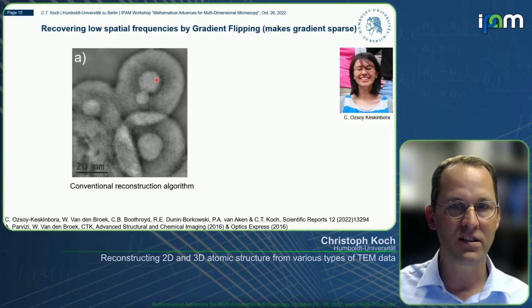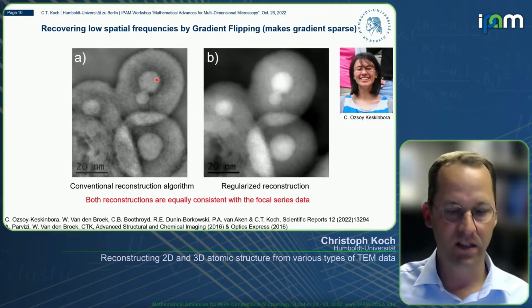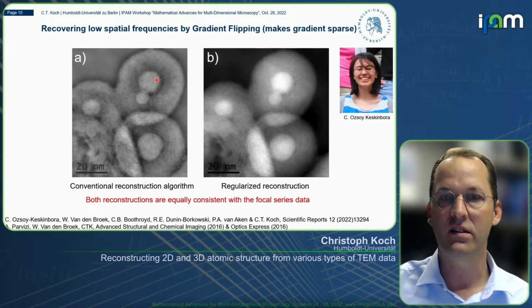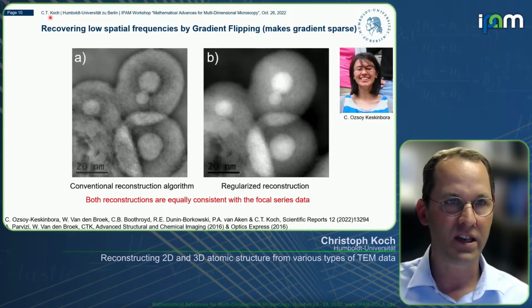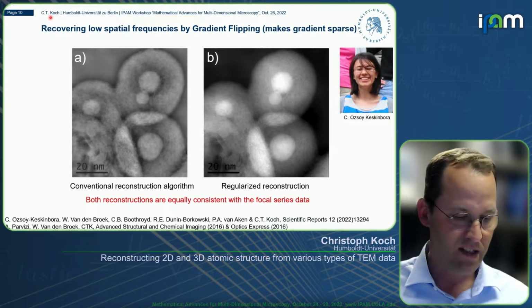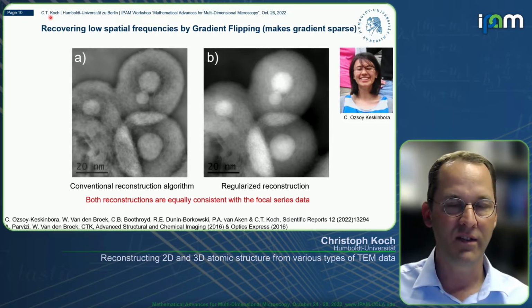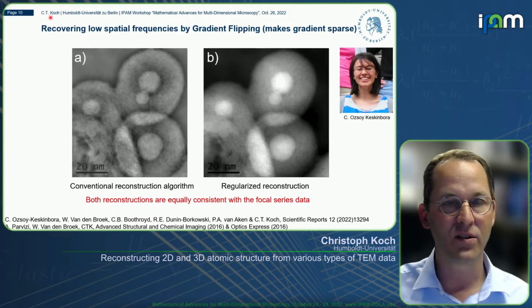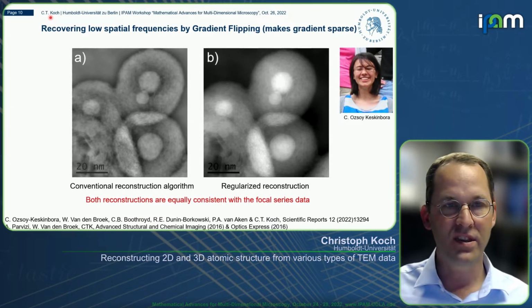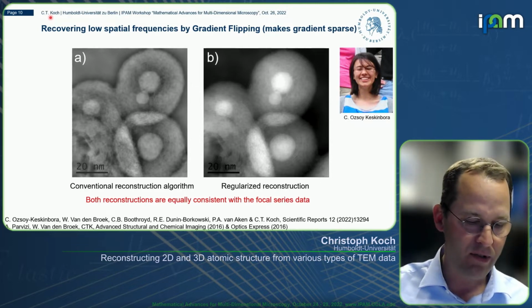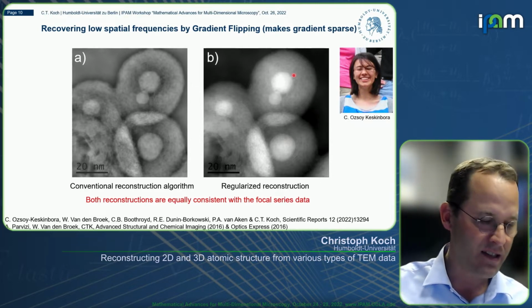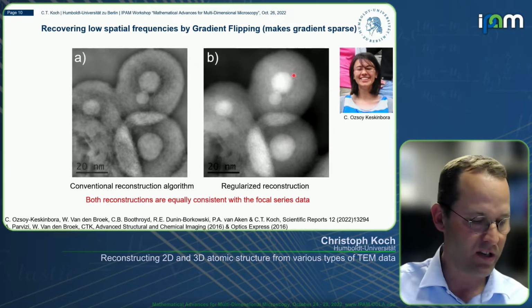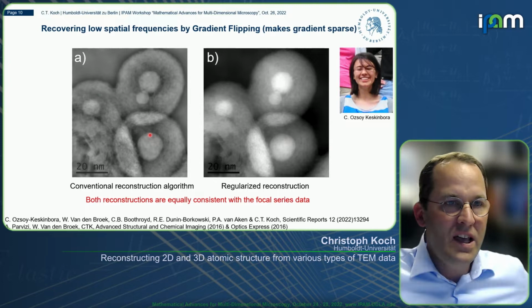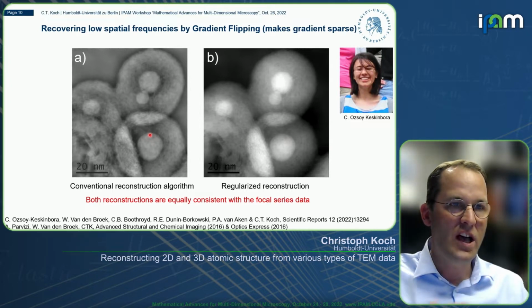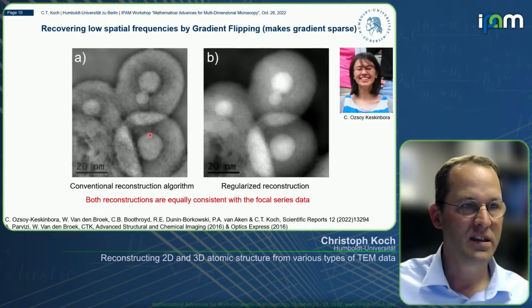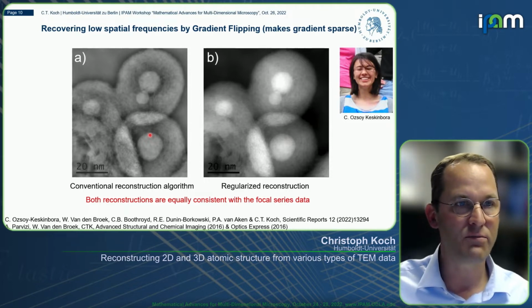And applying this flipping now not just to the density or the charge or the potential in our case, but to the gradient of that, allows us to then really somehow add information that was not extractable from the data. So the agreement of this potential map here with the data is the same actually as the agreement of the original potential map with the data. So we can now apply constraints to somehow help us add information that was not really available from the data directly.